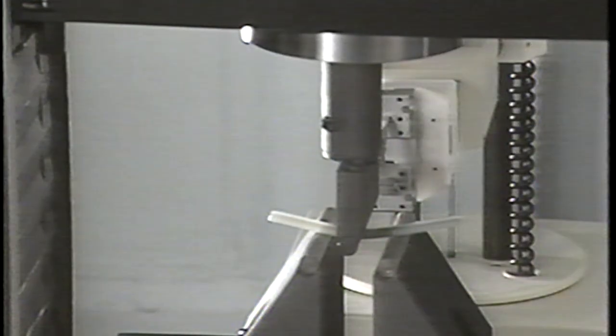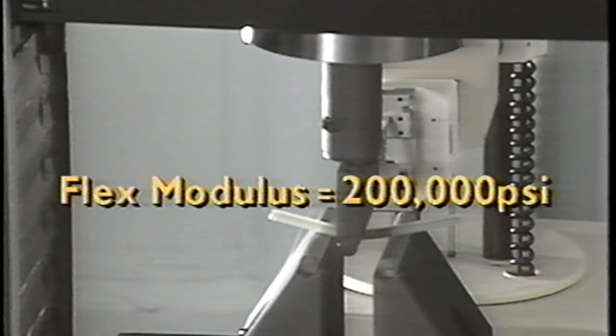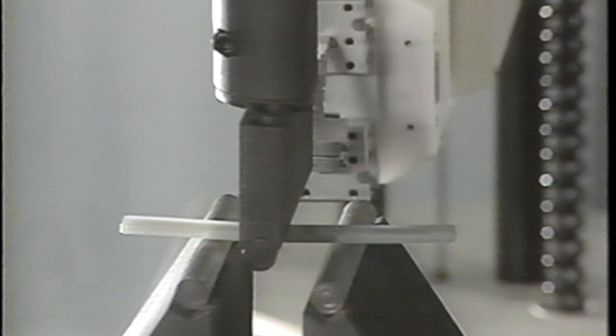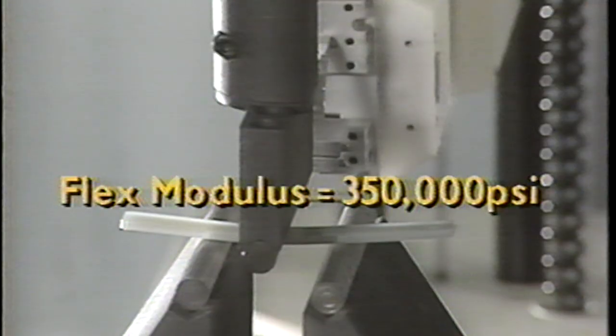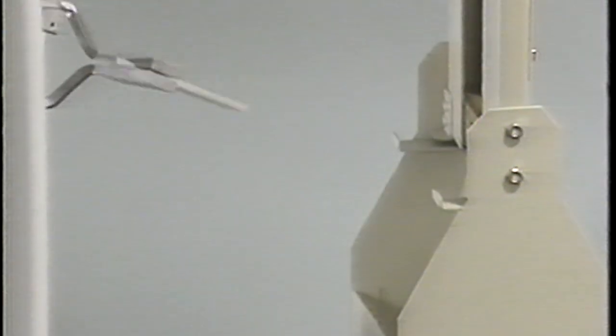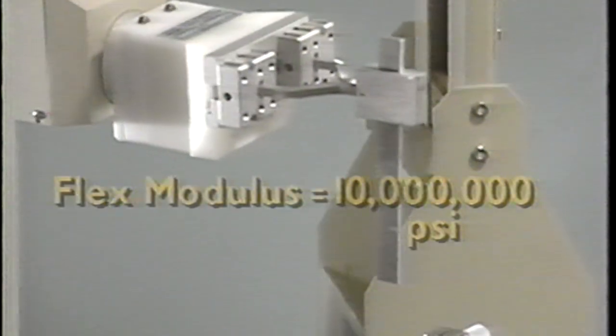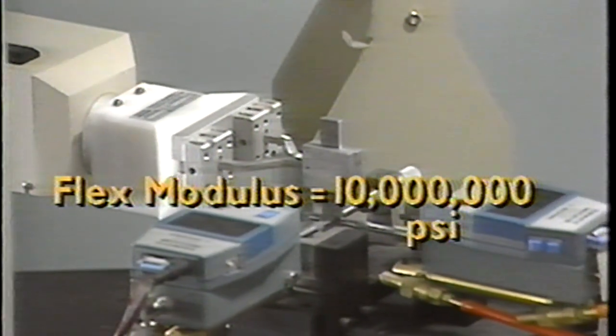Nylon, for example, tests at 200,000 psi, moderately stiff. Celcon polyacetal is much stiffer, with a flex modulus of about 350,000 psi. For comparison, this piece of aluminum comes in at about 10 million psi.